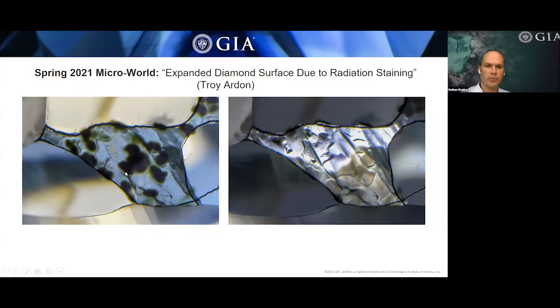And the radiation stains were so prominent that when you look at the registered photo pair in reflected light versus transmitted light, the transmitted light on the left shows the green color of the radiation stains, and the reflected light shows that wherever there's a radiation stain, the surface of the diamond is actually sort of blistered up or expanded due to the radiation damage. And so as the radiation damage is destroying the crystal lattice or creating this disorder in the lattice, it creates this expansion. And so you have this sort of plastic deformation of the surface area of the diamond. This was really quite an interesting example of this phenomenon.